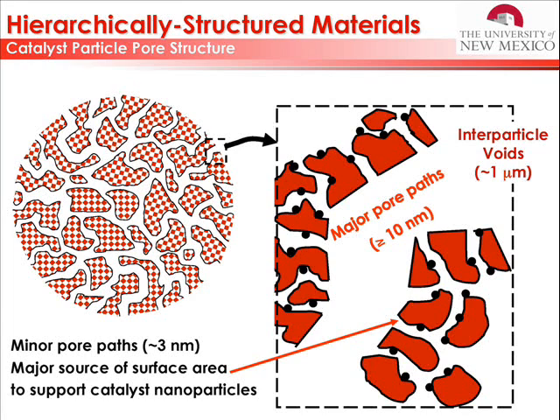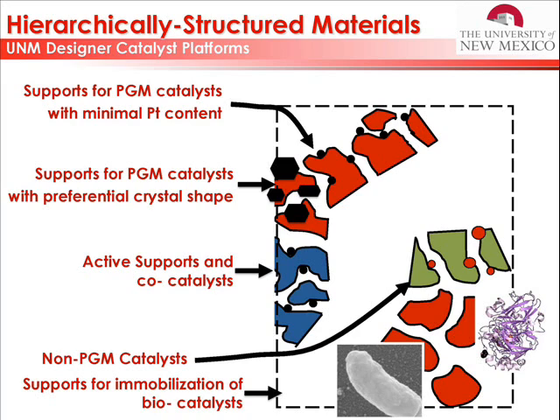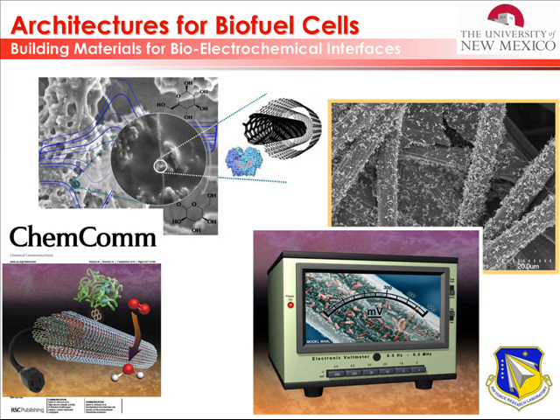Practically speaking, in order to design a good platinum catalyst, you have to design a defect-less surface. In order to design a good non-platinum catalyst, you have to design defects. So you have like two worlds that both work in the same direction, but they are dramatically different by the methods that you employ to achieve success. And that is actually bringing an even bigger differentiation between the platinum people and the non-platinum people. In that sense, practically speaking, nanometallurgy is needed to understand better and better platinum catalysis or platinum group metal catalysis. And actually, ceramics engineering of defects is needed to make better electrocatalysts that are of the non-platinum class. And I know that this laboratory has contributed to both quite dramatically over the last 25 years.